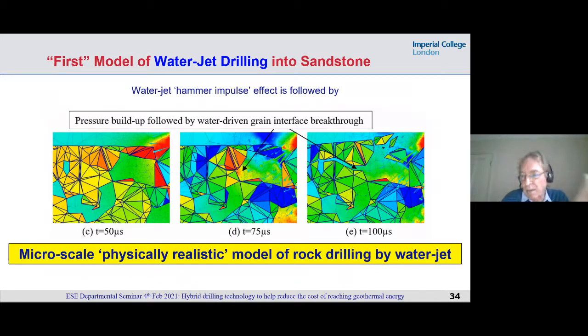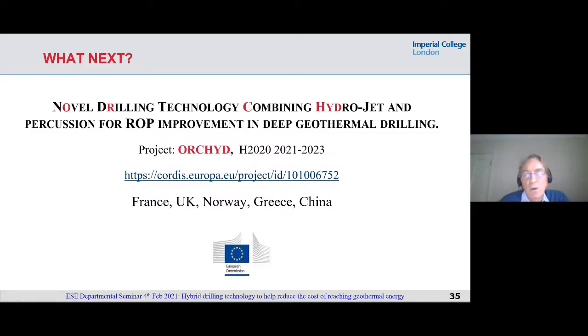So if we look thematically time slice by time slice, we can see the left-hand figure after 50 microseconds. It's really fascinating because you can see what's going on. If I put my mouse, that high velocity red zone is just breaking its way through into this big rectangular void, and at the next time step, 75 microseconds, that high velocity field is exerting its way into a grain boundary and beginning to push its way through, opening up, cracking, and you can see that sub-horizontal crack propagates and removes that fragment. So this is microscale, physically realistic modeling. So what next with this work?